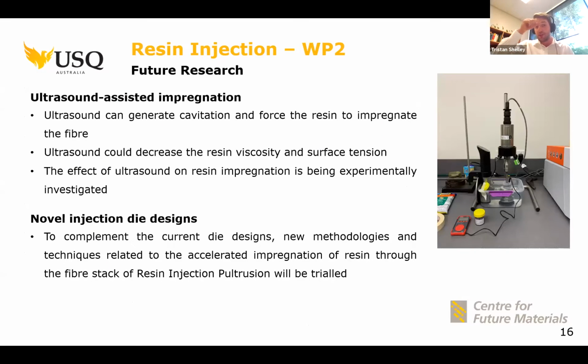Some future research which is happening is around looking at ultrasonic assisted impregnation, both looking at the ultrasonic treatment of the resin prior to injection, and also the excitation of the injection die for the improvement of resin wet out through the fiber stack, and also looking at novel injection die designs for the accelerated impregnation through the injection die as well.